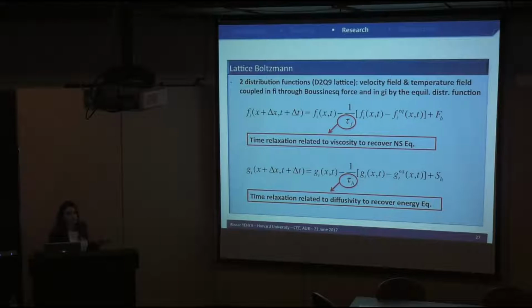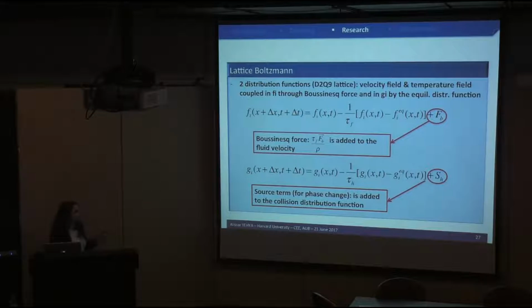And also here in the energy equation, we can relate this diffusivity to recover the energy equation. So we can add also forces. We can add the Boussinesq force to account for convection because we need it in our modeling. And here we add the source term to account for the phase change. So here's the model that we're modeling with mainly this set of equations.